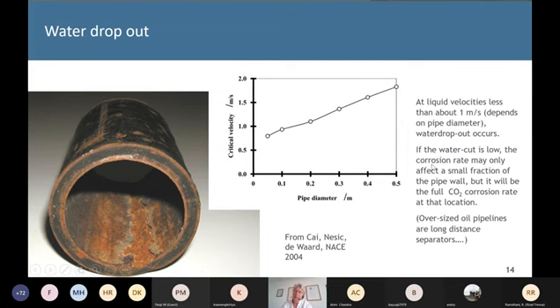But what we often see is that people oversize pipelines. It's a general trend of pipeline designers, and I always stress to people that if you don't get the velocities right, the risk of actually having a long distance separator between your fluids in and your fluids out is very high, and we see a distressing amount of damage on oil pipelines due to this problem.